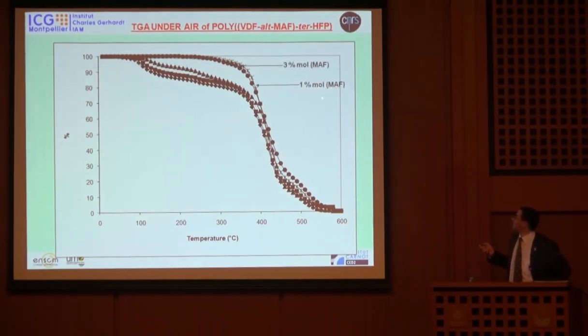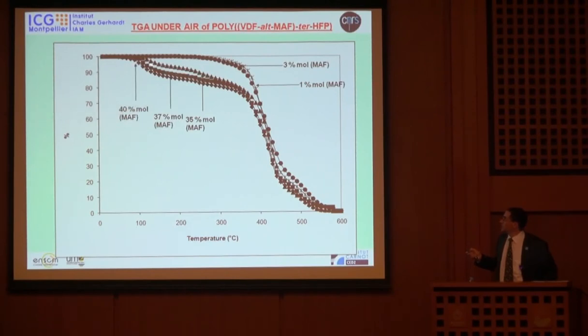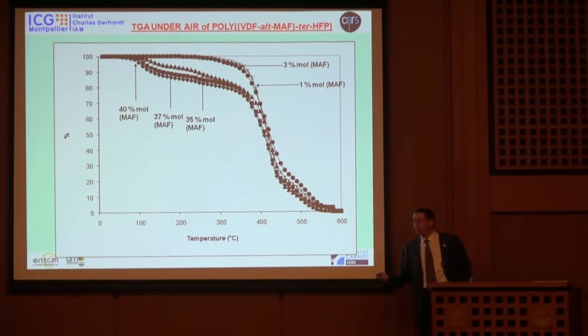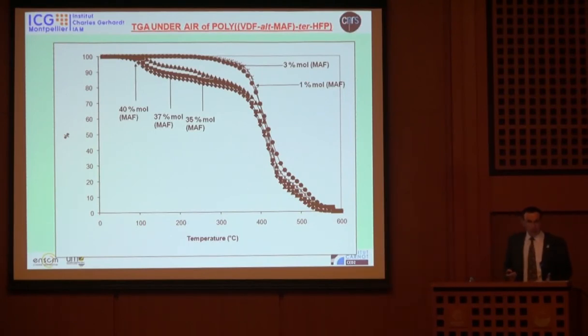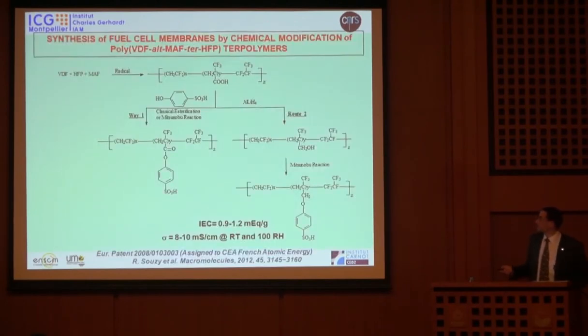Let's say here we have 1% of MAF, 3%, 35%, 37%, and 40%. So this means the higher MAF you put, the higher decarboxylation you have in your system, and you have a very poor thermostability. So this is a TGA where you heat under air. So the idea was, okay, to put carboxylic acid is not very good for conductivity. Can we modify this carboxylic acid in order to have sulfonic acid, for instance? And this is exactly what we did.